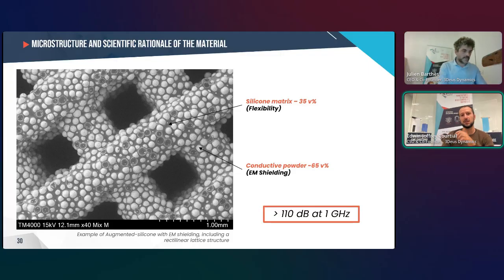So dynamic molding enables the design of enhanced silicone with a well-controlled biphasic structure: a silicone matrix of around 35 volume%, providing elasticity and compliance, and a micrometric powder of about 65 volume%, responsible for electromagnetic shielding. The specificity of this material lies not only in this ratio, but in the spherical morphology of the conductive particles. These spheres ensure excellent flowability of the powder when it acts as a dynamic mold, while simultaneously creating interstitial voids, or dead volumes, that allow the silicone to drain in and fill the structure during the processing, during the dynamic molding, I mean. This mechanism is essential.